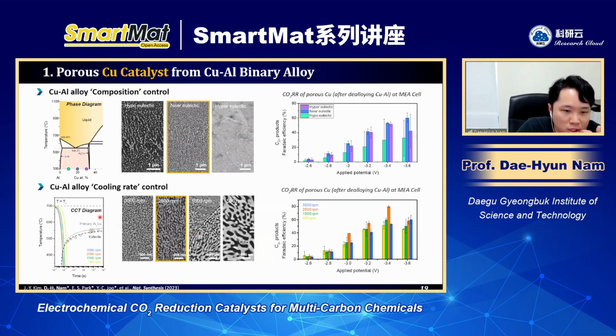By controlling the cooling rate, because the way we make this alloy is that after we mix the metals, we increase the temperature to melt these two solids into liquid. After that, we cool down to have a solid. By doing this process, we get the alloy fabrication. The cooling rate means the speed of the temperature decrease from the liquid to the solid state alloy. And as you can see, according to the cooling rate design, we could control the width of the lamellar structure, which is composed of aluminum and copper. So based on this procedure, we could get the optimal condition, which can produce C2 products with high FE.